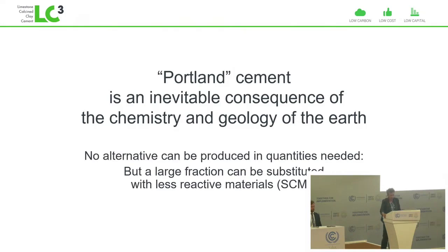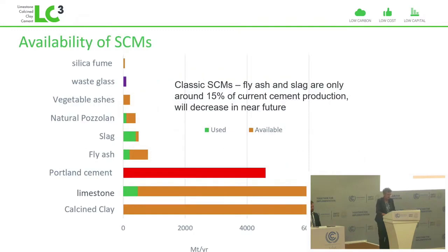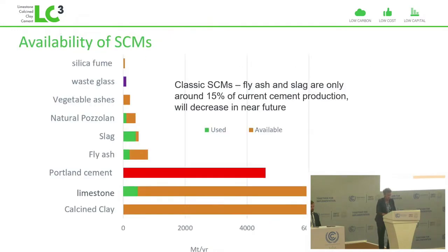But that doesn't mean we can't do anything, because we can very much do something. We can substitute a large proportion of these materials by what we call supplementary cementitious materials. So this idea has been around a long time, but today the materials we're using as replacements are what is called slag and what is called fly ash. So fly ash comes from burning coal, which of course is the first thing we've got to do to prevent climate change. And slag comes from the production of iron, where also it's really imperative to find better low-carbon solutions